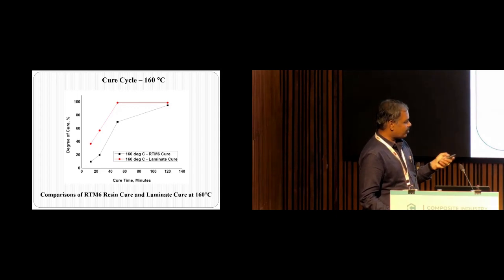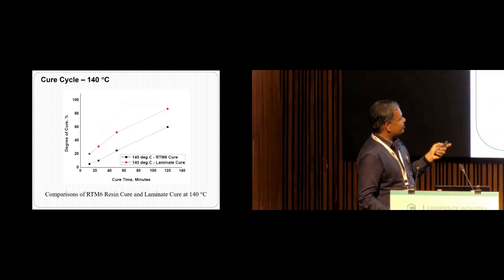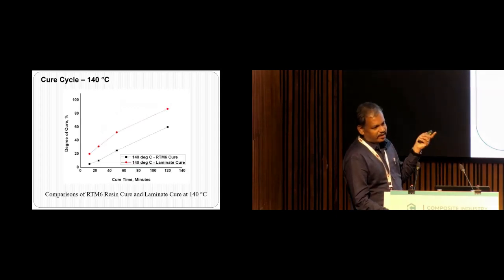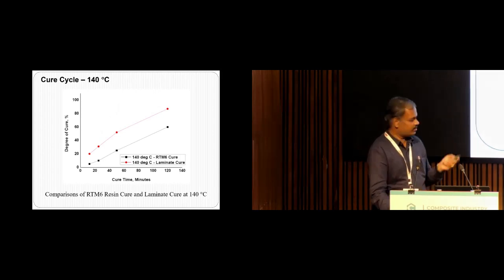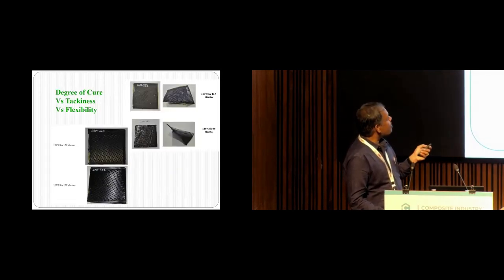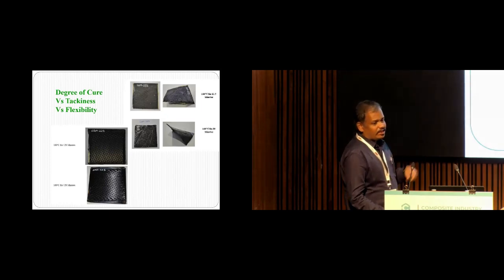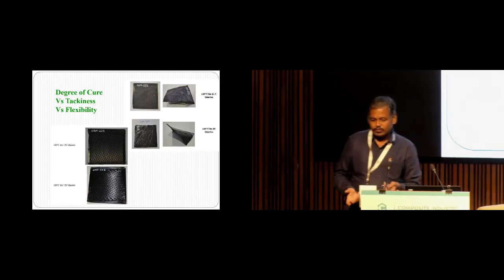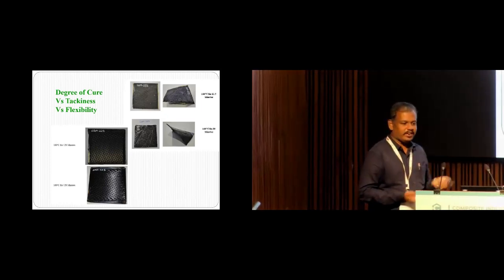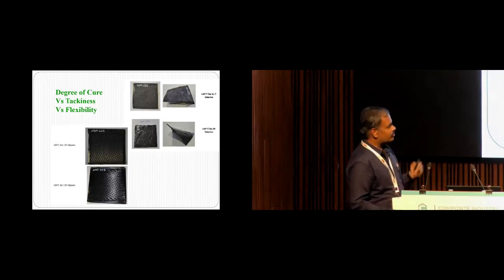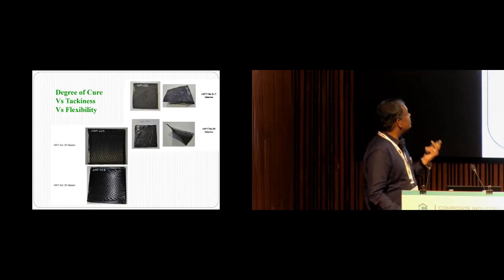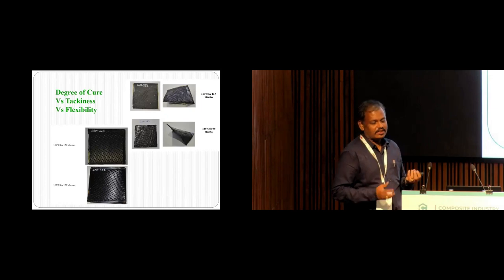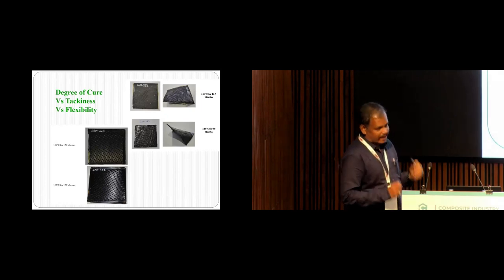It is the case of 160 degree centigrade. So when you go to 140 degree centigrade, the same trend is getting observed. Another important thing is that I have to manufacture semi-cured composite laminate and I have to transport it. So there are two important parameters: one is degree of cure and the physical consistency of the laminate.